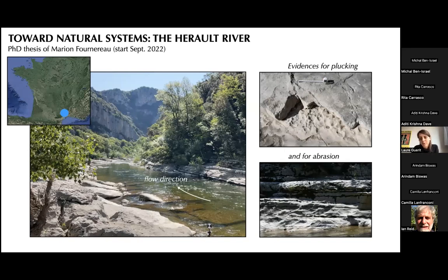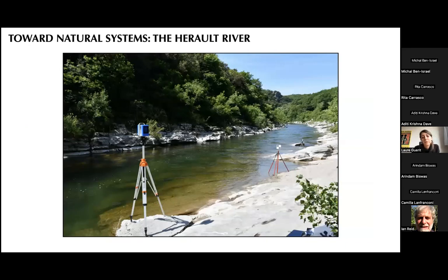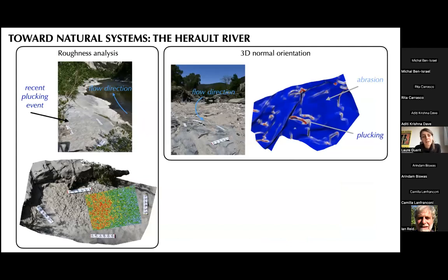And we also have a lot of abrasion, as you can see on this picture, with a smooth area here. So we went there last May, and we acquired some topographic data with terrestrial LiDAR, as you can see on this picture. We also did some photogrammetry, and our idea is to identify areas dominated by plucking from areas dominated by abrasion based on maybe the roughness of the rock. So here, for example, here is an area dominated by abrasion, and here we think it's a recent event of plucking. And you can see that there is a clear signal in terms of roughness.